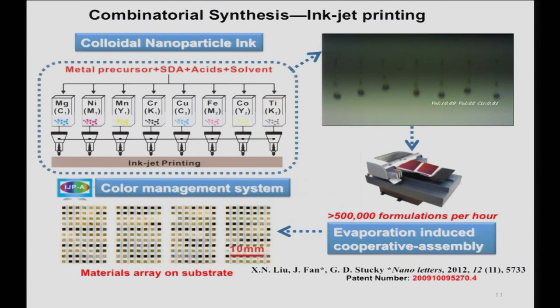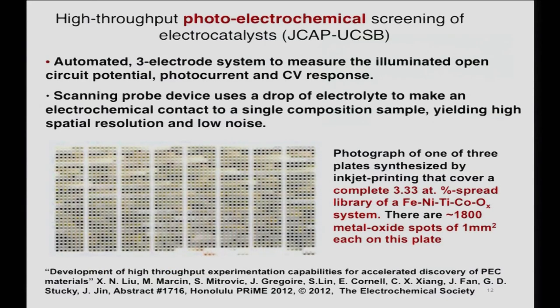So one approach, which came out from Gifon and my group, and also has been developed by, and is currently being used at JCAP, in collaboration with JCAP, is basically using inkjet printing, where you can get up to 8 different compositions, for example, which are shown here, and you can print them out very quickly to make screening. You can do photoelectrochemical screening, and this was a 3-electrode system, a scanning probe device, which was developed at Caltech and JCAP, using a drop of electrolyte.